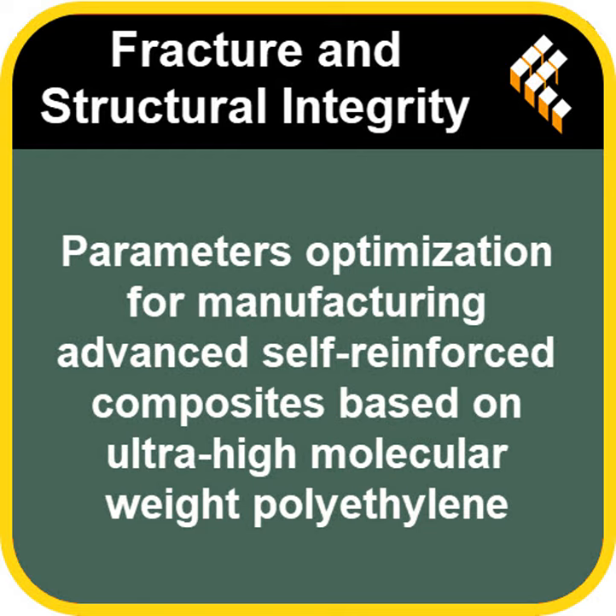Okay, next property. Impact resistance. How does this stuff handle a sudden hit? Does it shatter? This was really interesting. They used Charpy impact tests, which involve hitting a sample with a swinging pendulum. And the key finding was none of the samples actually broke completely. None? What happened then? They all just bent. They underwent plastic deformation, a permanent bend at the impact site. But the fibers themselves didn't fracture. So they absorbed the energy by bending, not shattering.